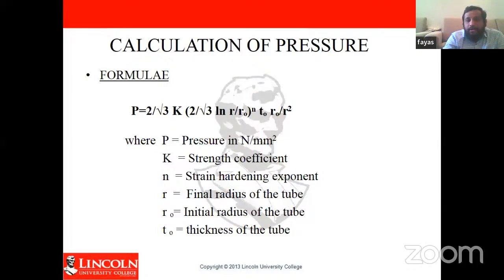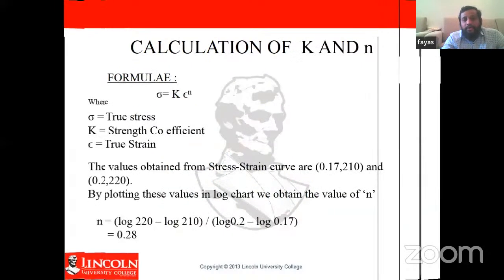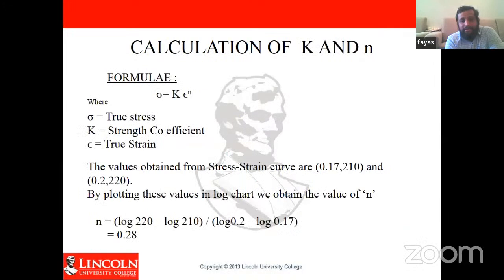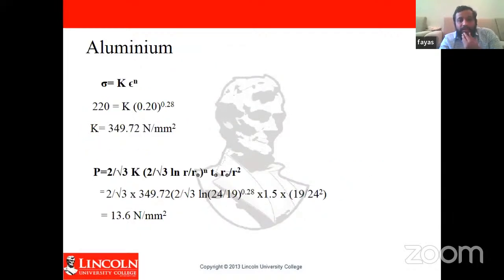This is the formula. The important point is we have to find the strength coefficient K and the strain hardening exponent n. The formula is: stress equals strength coefficient times true strain to the power n. The n value we will get from the stress-strain curve. This is the calculation for aluminum. We have given detailed calculation only for aluminum. So we got theoretical pressure as 13.6 Newton per millimeter square.